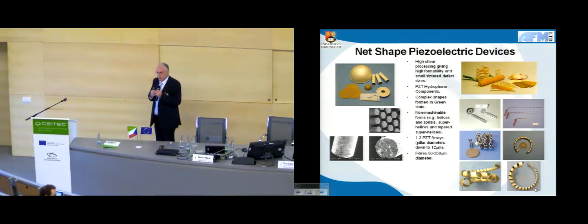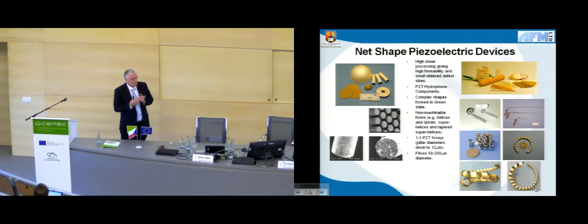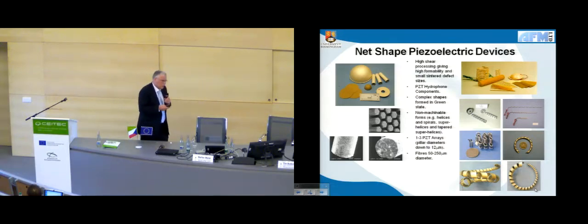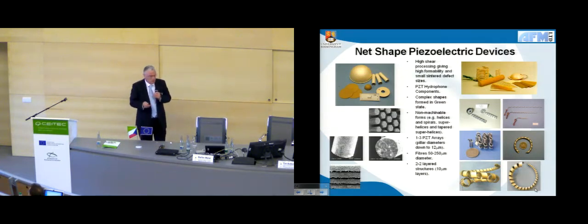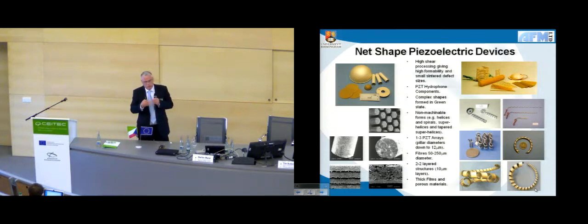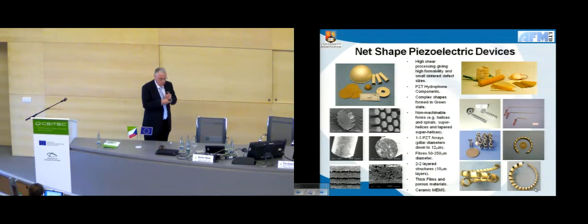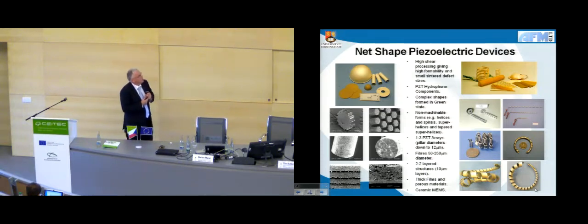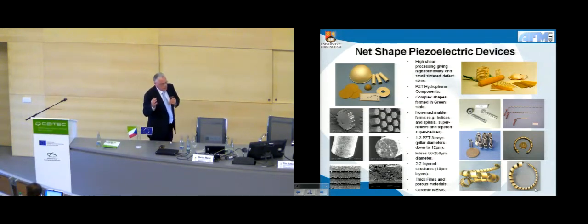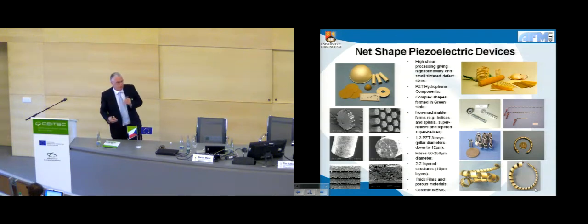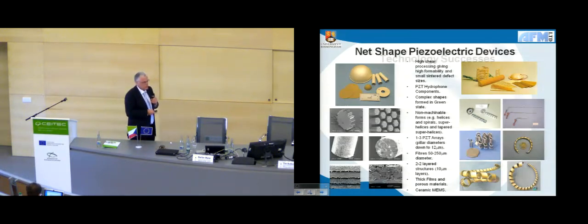Fibers are very useful for providing actuation and integrating in fiber composite materials. And we're able to show that you can do that in a range of functional ceramic materials. We can make layered structures. We can integrate dense structures with porous structures to change the properties. And we can even make very microscale ceramic components. This little gear, for example, is just a few hundred microns in diameter in a solid ceramic material. So this is very much the way that my research has gone, trying to make very complicated but useful shapes in functional ceramic materials.